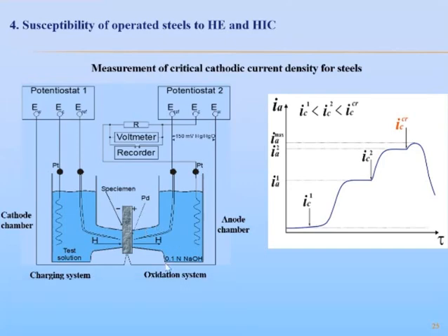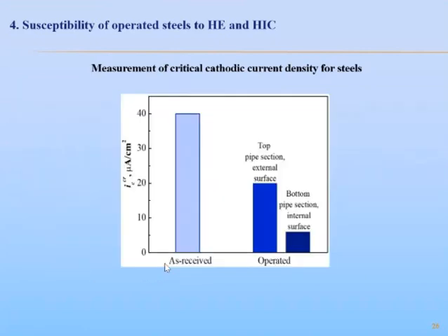And increasing cathodic current each time leads to an increment of anodic current density in the oxidizing cell. And at some point the layer of the membrane becomes damaged due to the combined action of hydrogen and residual stresses induced by intensive hydrogen charging. In such a case, a sharp decline appears on the oxidizing curve of the hydrogen output side of the membrane. This indicates the trapping of hydrogen with newly formed defects, that is, the development of hydrogen-induced damaging. Thus, the cathodic current density which corresponds to defect occurrence is considered as the critical one, and it allows determining the mechanical susceptibility to hydrogen-induced cracking.